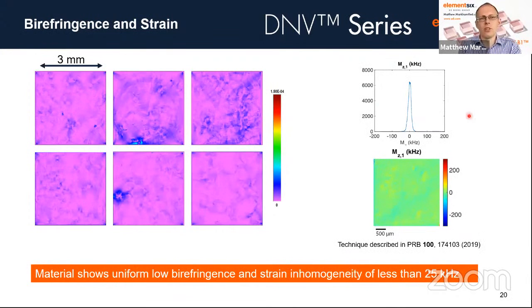Again, birefringence and strain. Actually, birefringence is probably more key in this material because, as we've reduced the nitrogen content, the dipole coupling from the residual nitrogens means that factors like strain are more important. So this material typically has a birefringence of less than 10 to the minus 5, which corresponds to a strain inhomogeneity of less than 25 kilohertz.